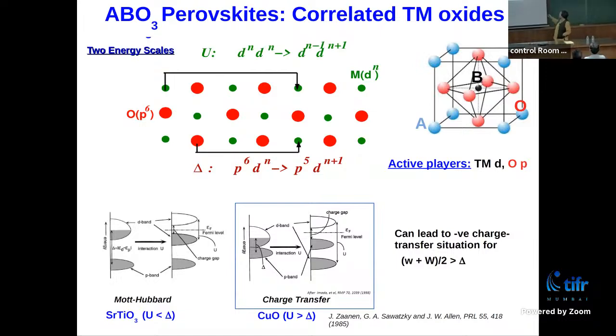And this can lead to a negative charge transfer situation, in the sense that if the bandwidth of this oxygen p band, small w, and the bandwidth of this upper Hubbard band, which is empty, big W, get overlapped, meaning (w + W)/2 is greater than delta, what you get is a metal with a partially filled oxygen band. That is known as a negative charge transfer situation.